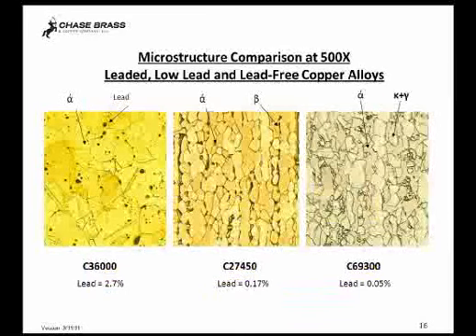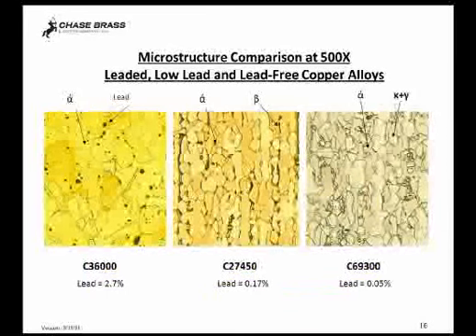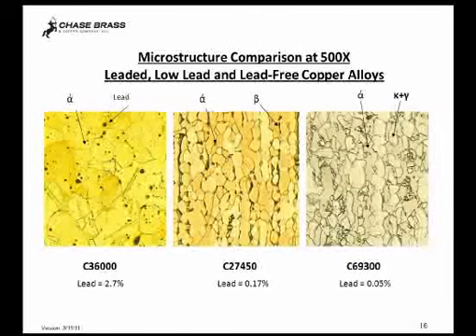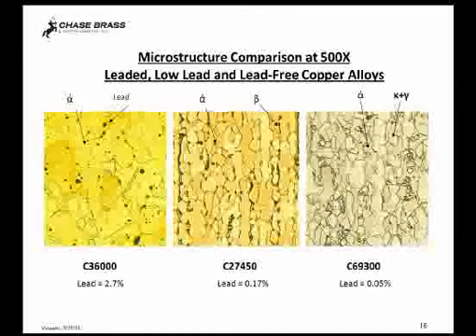When you look at the impact of lead on the different kinds of brasses that are there, alloy 360, which in this case has 2.7% lead, is a combination of brass, a uniform copper and zinc mixture called alpha phase, and then lead particles. Alloy 27450, which in this case has 0.17% lead, there's really hardly any lead there to see. These tiny little specks are lead particles.